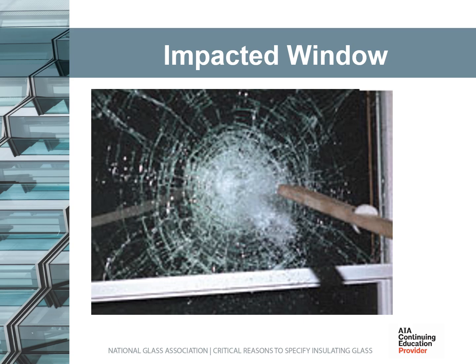Part 2. The cycling portion of the testing is then conducted on the same test window to ensure that a window having withstood impact by the 2x4 can then stand up to rapid increases and decreases in pressure within the building during a hurricane. Within the laboratory setting, this is done by introducing 9,000 cycles of differing pressures to the impacted unit. Common test methods and standards surrounding hurricane testing are State of Florida TAS 201, 202, and 203, ASTM E1886 and E1996, AAMA 506, Miami-Dade County testing protocols, etc.